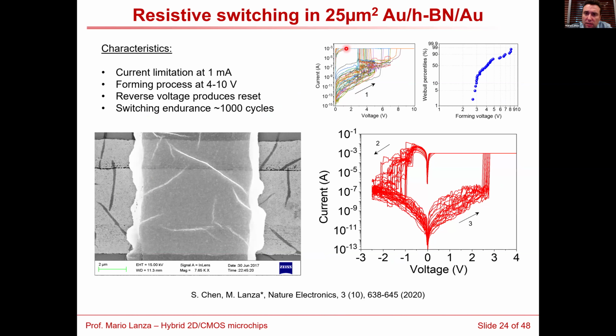After that, we apply a current limitation of 1 mA. And after that, if we apply a reverse voltage, we observe that the current is reduced. And then if we apply a subsequent positive ramp, we observe a dielectric breakdown again, this time at lower voltages than here. And this can be repeated cyclically for hundreds of cycles. And basically, this is the confirmation that this device exhibits non-volatile bipolar resistive switching, okay?